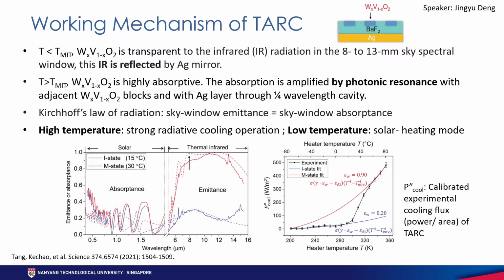Because of the temperature change, if the temperature is lower than 22 degrees Celsius, the tungsten vanadium dioxide is transparent to the infrared radiation. It is in an insulating state, so the infrared will be reflected by the silver layer. If the temperature is higher than 22 degrees Celsius, it will be highly absorptive for the infrared radiation. The absorption will also be amplified by photonic resonance with the blocks and the silver layer. So for TARC, at high temperature, it will show a strong radiative cooling operation mode, and at low temperature, it will show a solar heating mode.